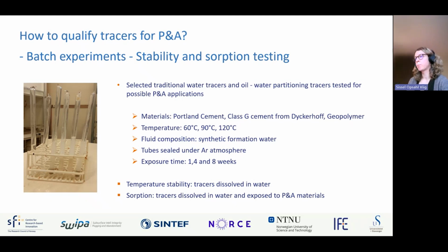And then for the batch experiments, we have 2 sets of experiments. One is purely temperature stability investigation, where the tracers are dissolved in the water, but with no barrier material present. And the other are experiments to study sorption or other interaction between the tracer and the barrier material. In these experiments, the tracers are dissolved in the water and crushed barrier material is added to the samples. And they are exposed for up to 8 weeks at the 3 different temperatures.